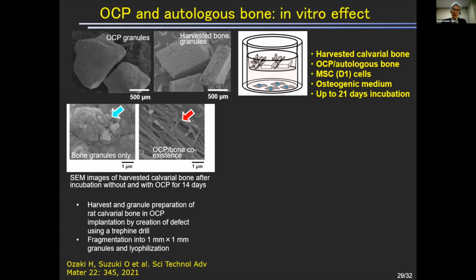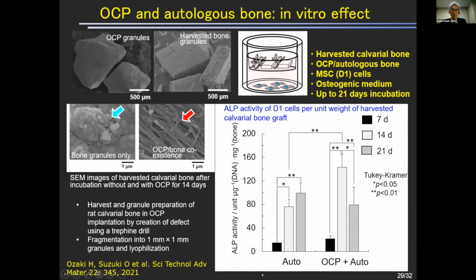So we analyzed the differentiation of the D1 cells, and this is a result of ALP activity. And you see, we mixed OCP with autologous bone. This condition enhances the osteoblastic differentiation of MSC. This is a result standardized by the autologous bone per weight. So this means that the OCP could enhance the osteoblastic differentiation existing in the bone. This result suggests the mutual chemical effects of OCP and autologous bone.